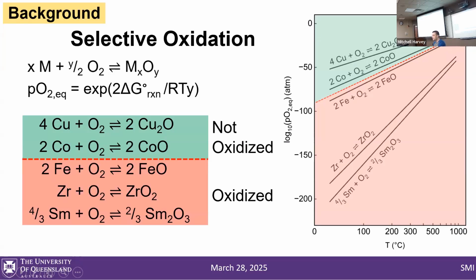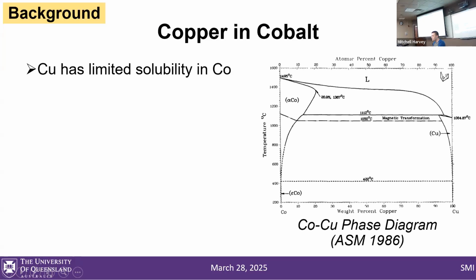And we don't want to do that. We're trying to retain the cobalt as a metal. So what do we do? Well, fortunately, copper has limited solubility in cobalt. If we look at the phase diagram, below about 500°C, there's almost no solubility of copper in cobalt.